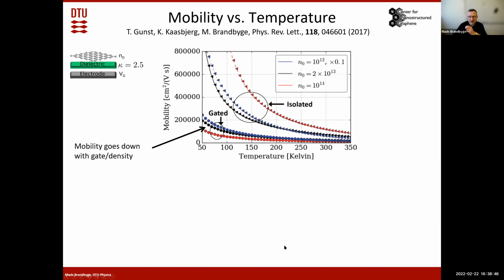And interestingly enough, if we include this gate, sort of realistic gates, so compared to realistic doping values, you see that actually the mobility is dropping down from something which is maybe a factor of 5 or so above what you see in experiments to mobilities which are much closer to what you see in experiments. Of course, this